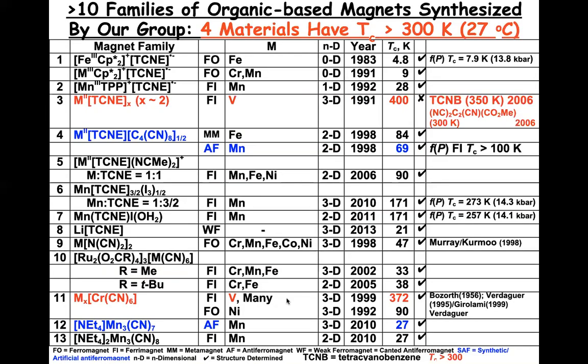And today we've got about 10 or 11 classes of magnetic materials. We talked about decamethylferrocene TCNE ordering at 4.8 Kelvin. We talked about vanadium TCNE ordering at 400 Kelvin. We talked about manganese TCNE half a C4(CN)8 being an antiferromagnet ordering at 69 Kelvin. Talked about TCNE manganese with triiodide ordering at 171 Kelvin. But you can see that I was willing to talk about more compounds and still have many more besides those that I wasn't going to talk about.